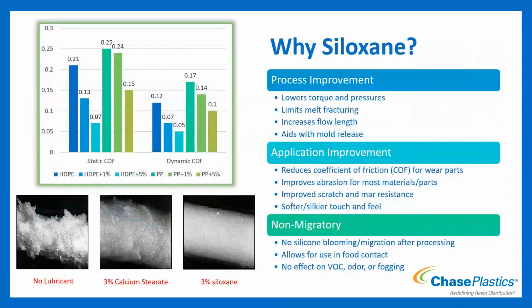Okay, so why would you use a siloxane or silicone-based slip agent? It's going to help process improvement. So we're going to lower some torques and pressures. It's going to slip a little easier. You're going to reduce your melt fracturing, which you can kind of see in the picture down here on the left. You can see no lubricant here, a different lubricant that's not silicone based, and then your silicone based. This is the surface of an extrudate coming out of the extruder. You see it's kind of breaking up a little bit, not holding itself together super well, versus using the siloxane, much less melt fracturing happening, a much smoother surface coming out of your extruder.